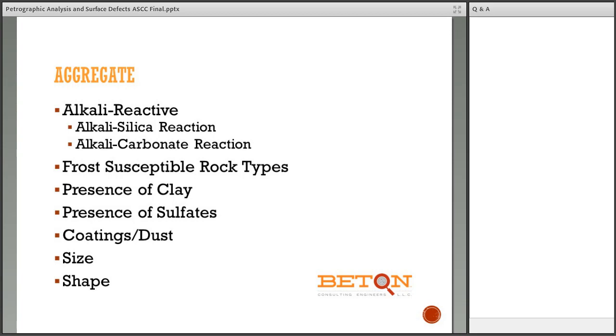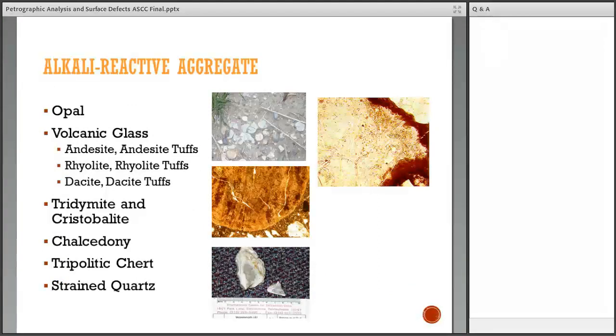We also look for frost susceptible rock types, presence of clays, presence of sulfates, coatings and dust on the aggregate, size, shape, and then we report that. And then basically for alkali aggregate reactive aggregates, we look for such things as opal, like opaline shales that we have around in Minnesota, volcanic glasses, tridymite and cristobalite, chalcedony, tripolitic cherts, and even strained quartz can be considered alkali reactive, depending on the amount of strain.